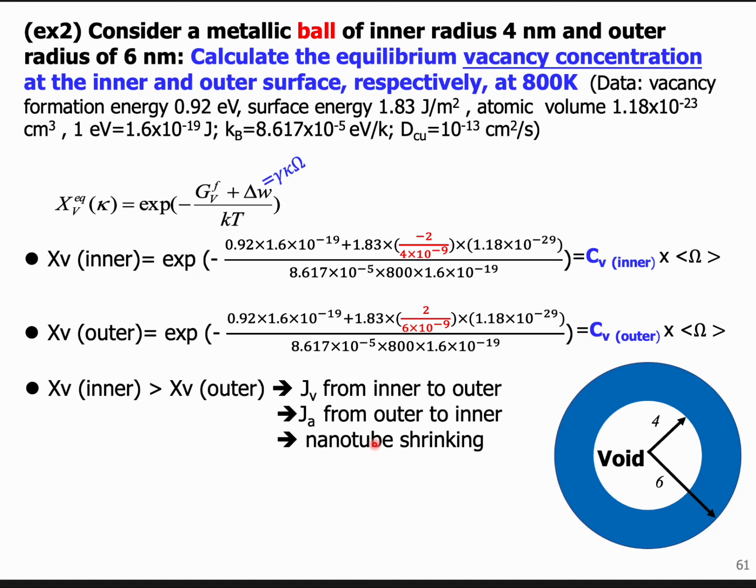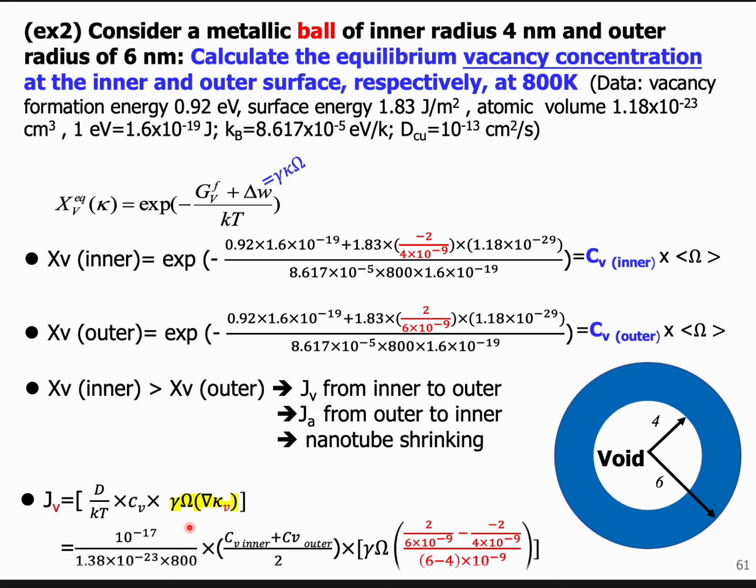Next, can you try to formulate the vacancy flux? The vacancy flux can be expressed by mobility, vacancy concentration, and the driving force. What's the driving force here? It will be the gamma, omega, kappa gradient, right? We mentioned this before, so you can put the parameters inside.